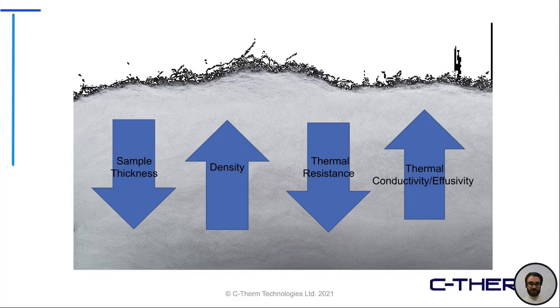So when you are dealing with something that's extremely compressible, and in this example here, you can see it's like a filler material that you might see in a jacket or some other product like this, you can imagine that as your sample thickness decreases, you're going to essentially be increasing the density, or the localized density in this case, over the measurement area. Through the increase of density, this decreases the overall thermal resistance in the sample, and this results in an increase to your thermal conductivity and effusivity measurement. So you see how these properties all play together and influence your overall measurement of that sample.